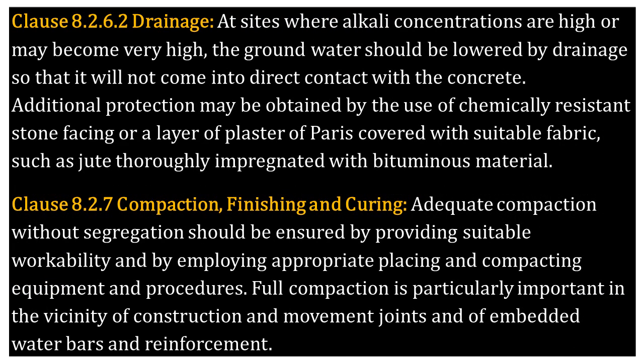In clause 8.2.6.2, drainage: at sites where alkali concentrations are high or may become very high, the groundwater should be lowered by drainage so that it will not come into direct contact with the concrete. Additional protection may be obtained by the use of chemically resistant stone facing or a layer of plaster of Paris covered with suitable fabric, such as jute thoroughly impregnated with bituminous material.